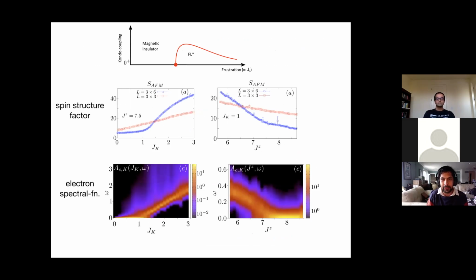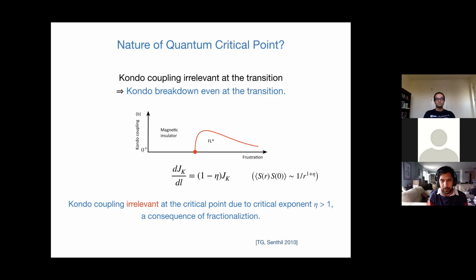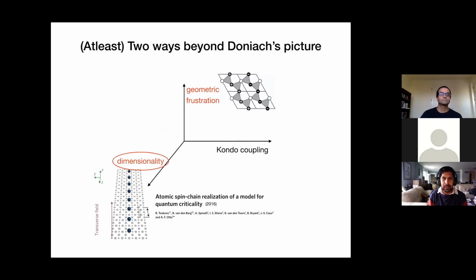But this is the physics you get, and you can study the critical point also, and you can argue based on RG that even at a critical point, Kondo coupling is ineffective precisely because of fractionalization. The Kondo coupling RG at a critical point involves the critical exponent eta of the spins, and eta is bigger than 1 in fact, because this is a fractionalized phase, and Kondo coupling is irrelevant even at the critical point. So there's an interesting consequence even for the critical point.